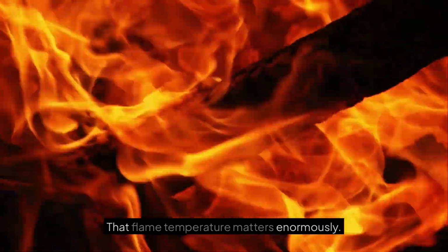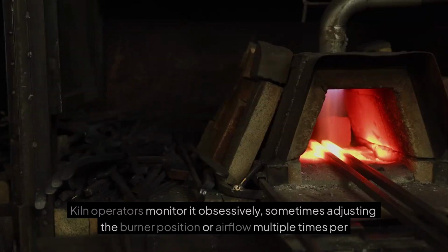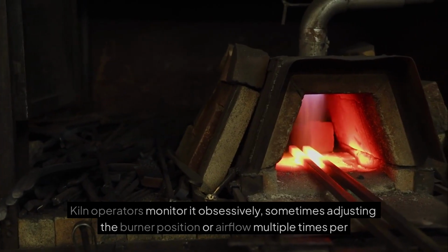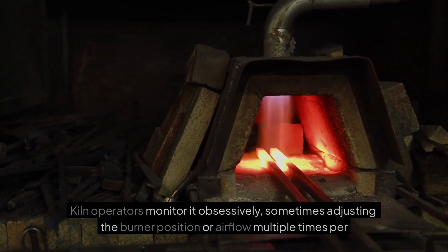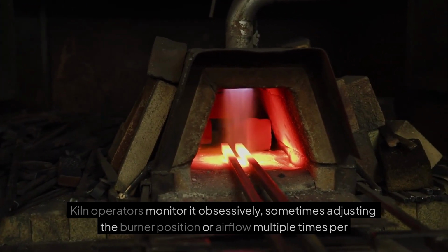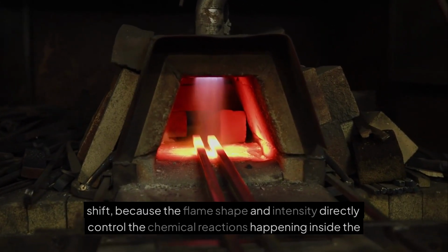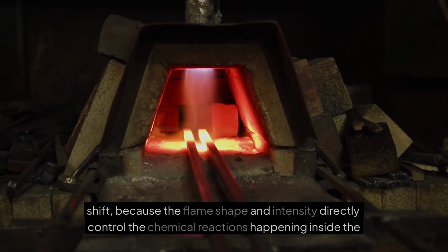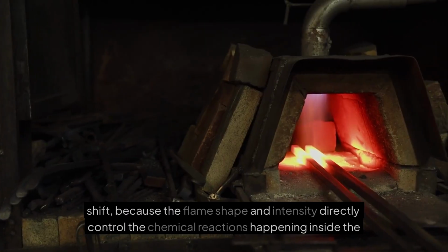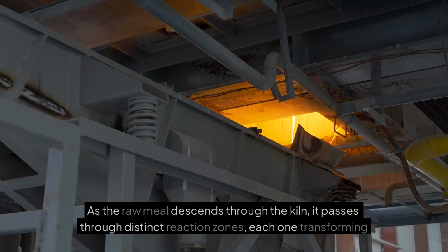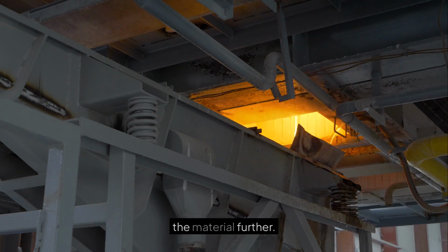That flame temperature matters enormously. Kiln operators monitor it obsessively, sometimes adjusting the burner position or airflow multiple times per shift, because the flame shape and intensity directly control the chemical reactions happening inside the material bed. As the raw meal descends through the kiln, it passes through distinct reaction zones, each one transforming the material further.